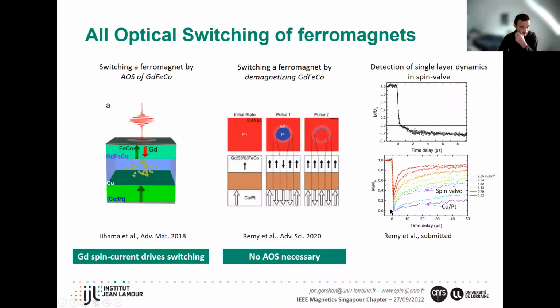And we relate this to the fact that you're injecting a strong spin current from the gadolinium iron cobalt that helps the cool down. So we have a paper coming out that explains a little bit how you can actually use the spin currents to accelerate the dynamics and avoid the very slow, the slowing down that you get when you get close to the Curie temperature. So we can get ultra fast switching, and we can get this ultra fast cooling with the spin injection.